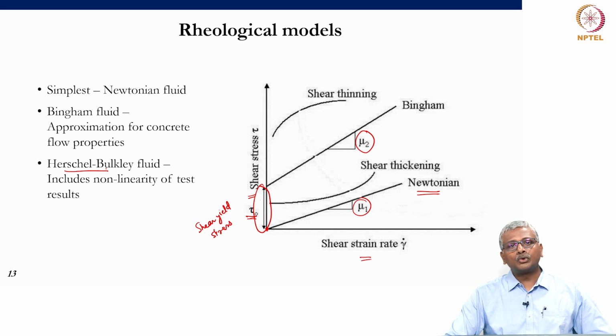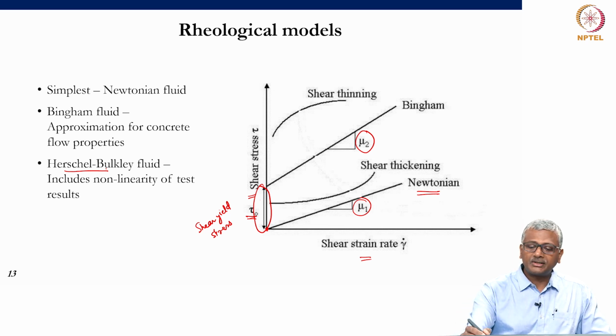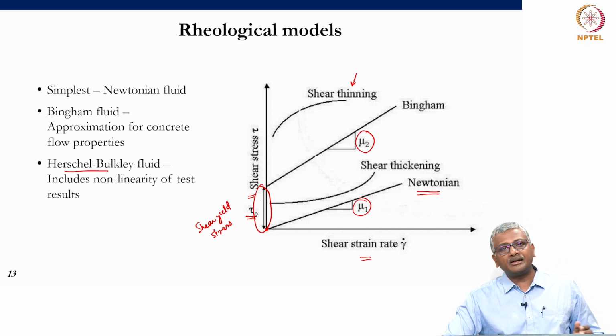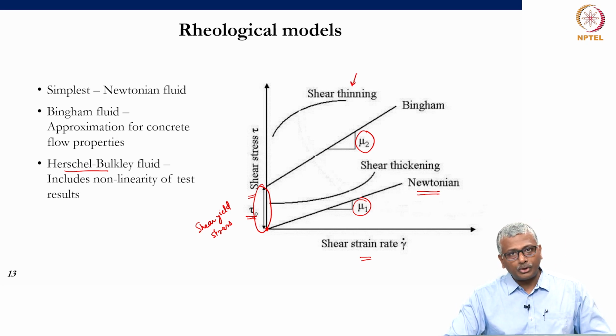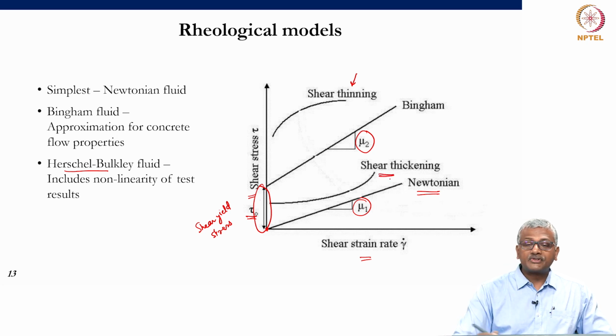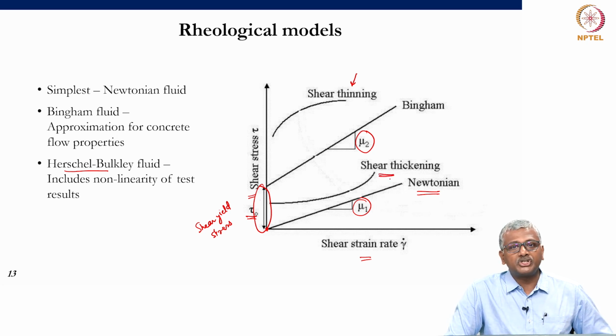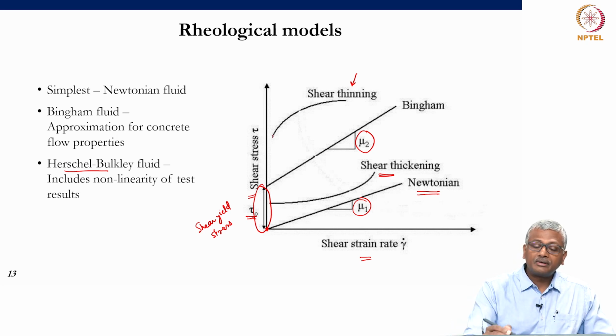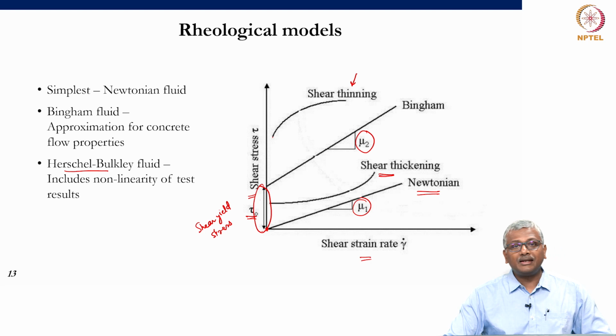In such cases, you do not have a constant viscosity, but the viscosity then changes as a function of the shear rate. In concrete, mostly what we see is a shear thinning behavior, where as the shear rate increases, the viscosity tends to drop. Okay. On the other hand, for certain gums and glues, you may end up having a shear thickening behavior, where when you increase the shear rate, your viscosity tends to go up. But in both these cases, the curve may or may not start from the origin, indicating that the suspensions may have some inner shear yield stress that needs to be overcome for flow to initiate.